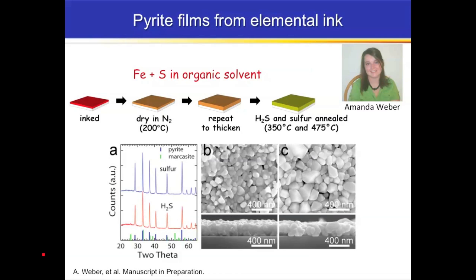One we call the elemental ink, and this is work done by Amanda Weber. Basically, we take elemental iron and elemental sulfur, and we dissolve them in a simple organic solvent. This yields a viscous black paste that we can deposit onto a surface and cook. She has a certain process scheme that ends up being sulfurized in two steps. This is the same kind of morphology that you would have seen for the CVD films. We can grow very nice films that are of the appropriate thickness to absorb all sunlight, and we characterize them in the same ways.